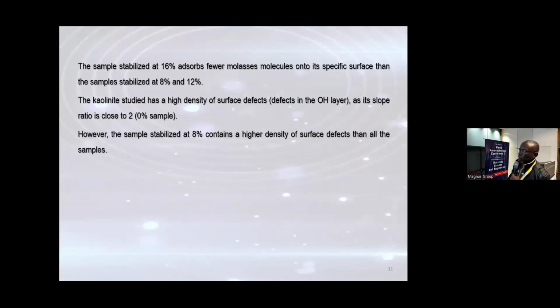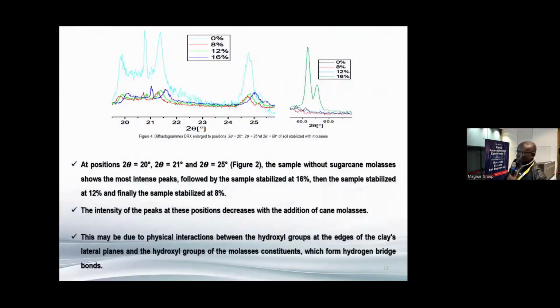The sample stabilized at 16% adsorbs fewer molasses molecules onto its specific surface than the sample stabilized at 8% and 12%. The kaolinite studied has a high density of surface defects, its slope ratio is close to 2. The sample stabilized at 8% contains a higher density of surface defects than all other samples. The sample without sugarcane molasses shows the most intense peaks, followed by the sample stabilized at 16%, then the sample stabilized at 12%, and finally the sample stabilized at 8%. The intensity of the peaks at these positions decreases with the addition of cane molasses.